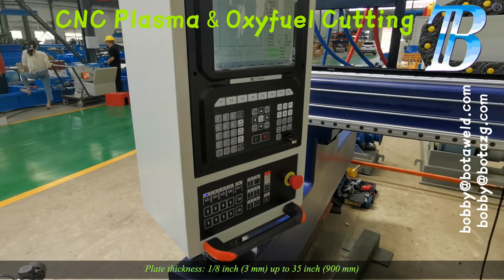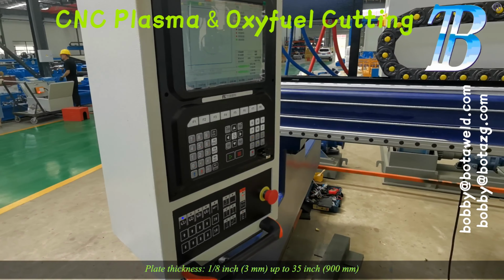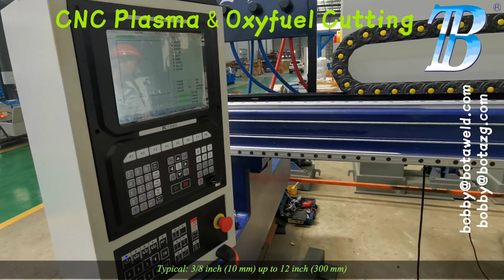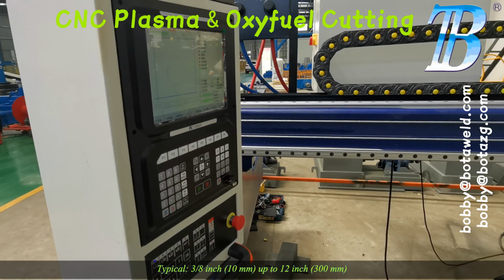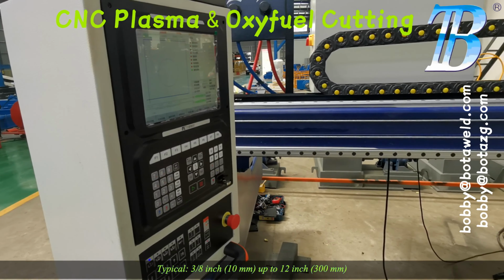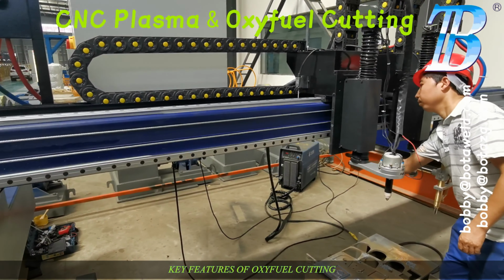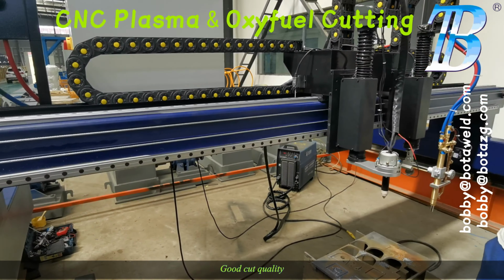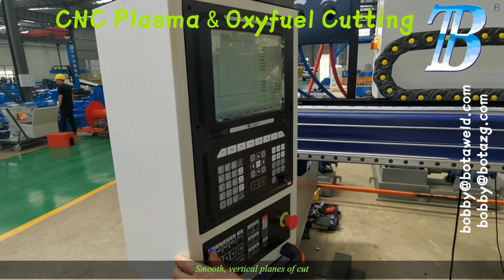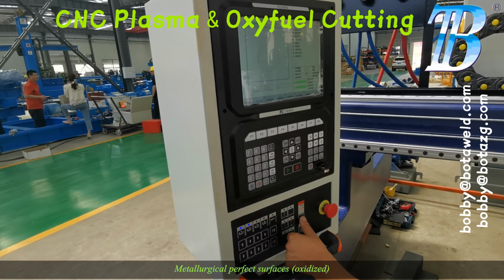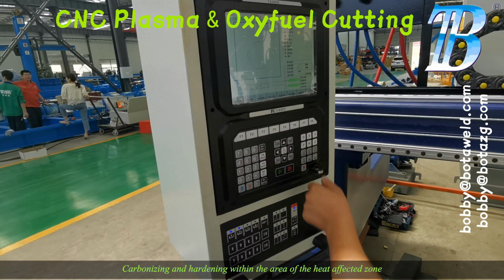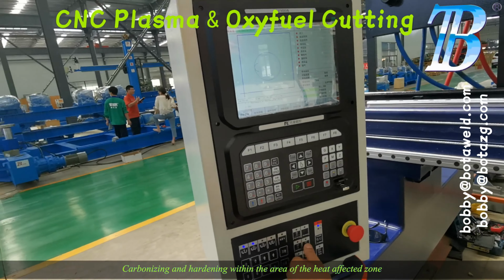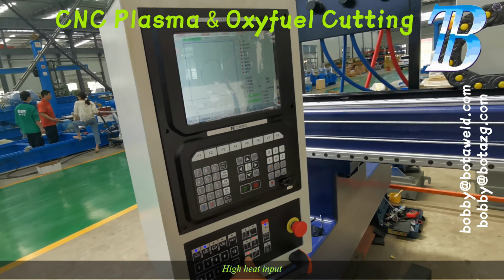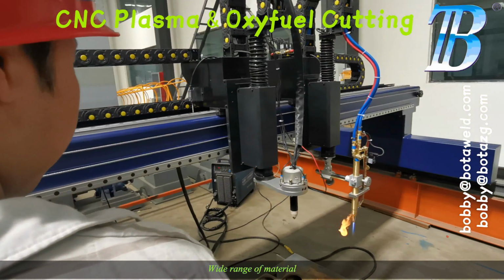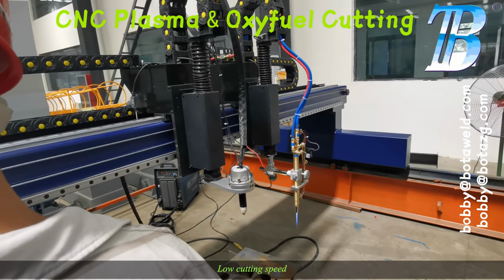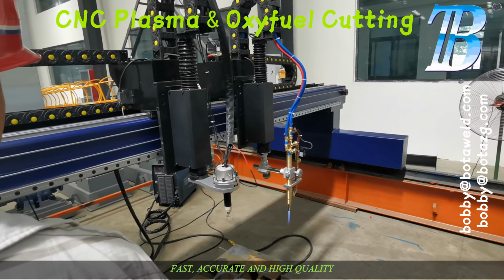Plate thickness 1/8 inch (3 mm) up to 35 inches (900 mm). Typical 3/8 inch (10 mm) up to 12 inches (300 mm). Key features of oxy-fuel cutting: good cut quality, smooth, vertical planes of cut, metallurgically perfect surfaces, oxidizing, carbonizing and hardening within the area of the heat-affected zone, high heat input, wide range of material, low cutting speed.